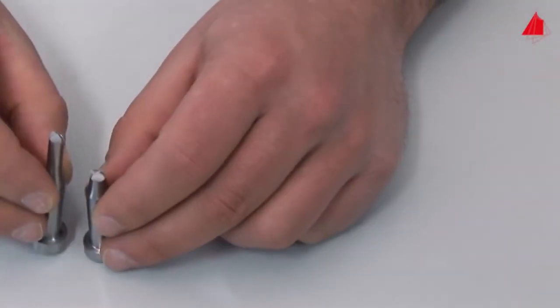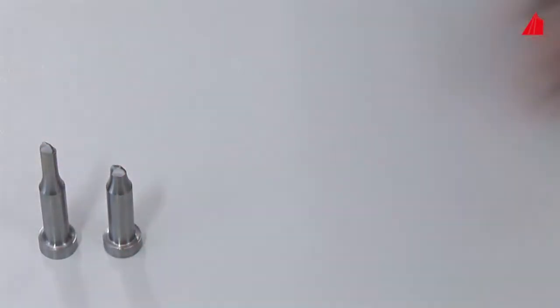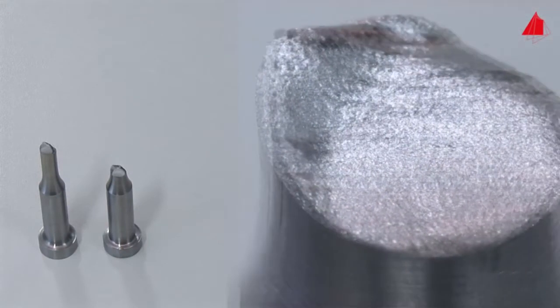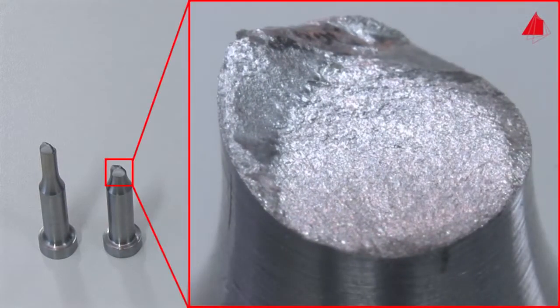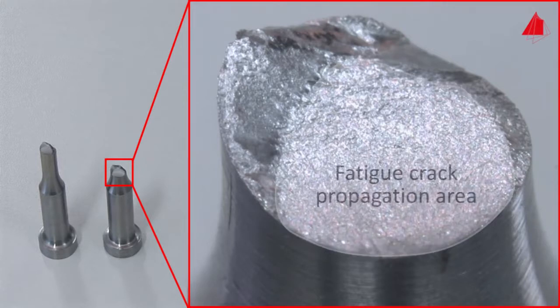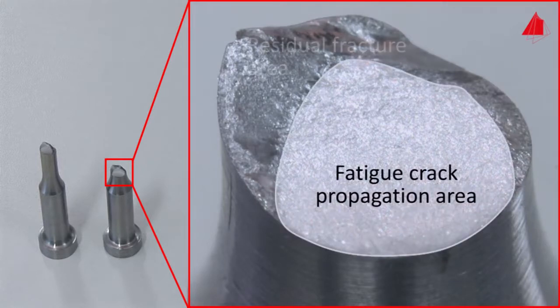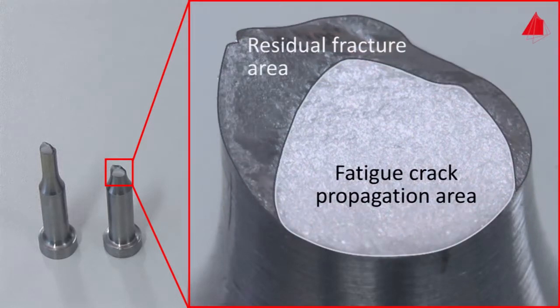At first glance, the fracture surface looks unimpressive. A closer look reveals 2 regions: the rather dull, predominantly flat fatigue crack propagation area and the rough residual fracture area. The residual fracture area results from the final catastrophic rupture. The fatigue crack propagation area has developed during the cyclic growth of the fatigue cracks starting at the surface of